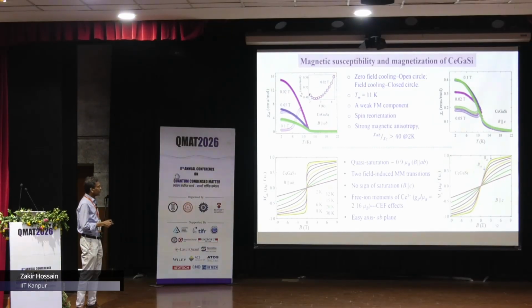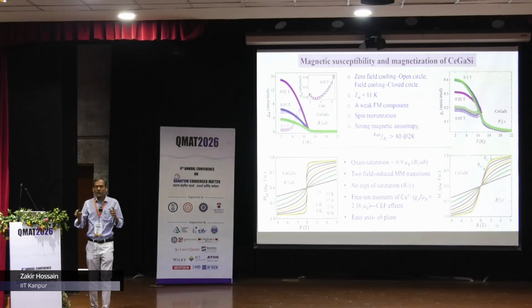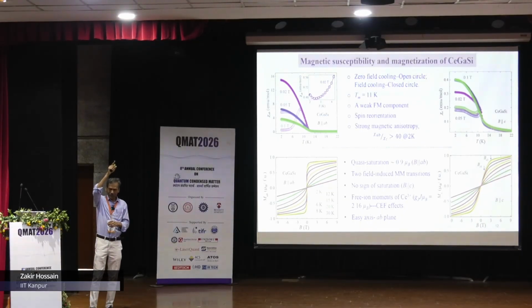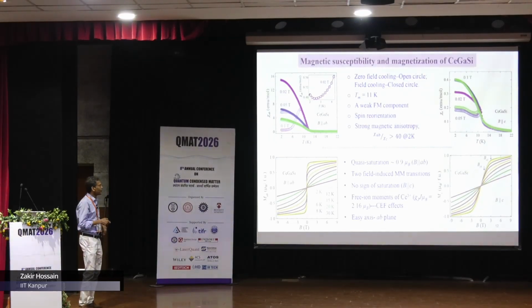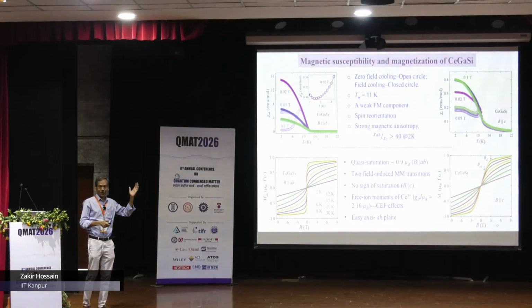So the structure, if you see the B parallel C, for example, it increases, goes to a maxima, and then decreases, and then some kind of a plateau, and then saturates. So typically, if it is a compensated pure antiferromagnet, you will see that maxima and then sharply decrease towards 0 as you cool the sample to lower temperature. That's not the signature, and it's not like a ferromagnet also, where it will increase and then saturate.